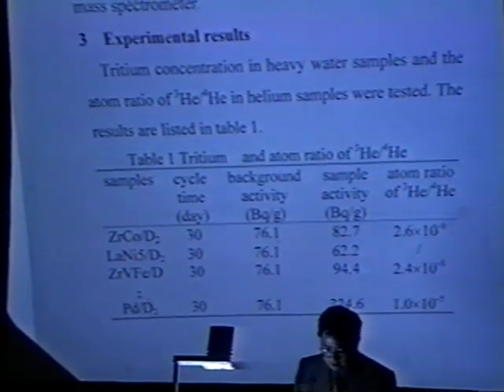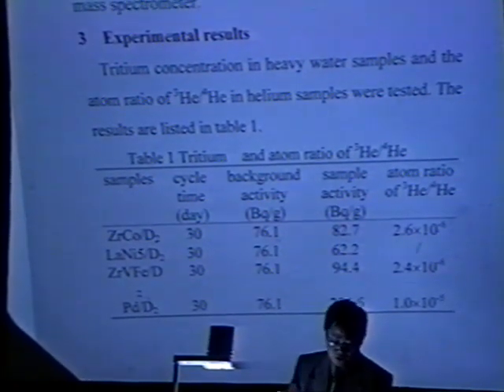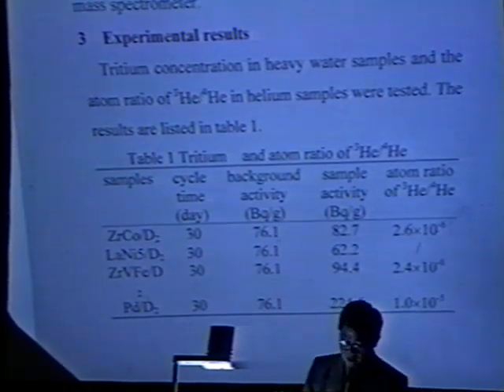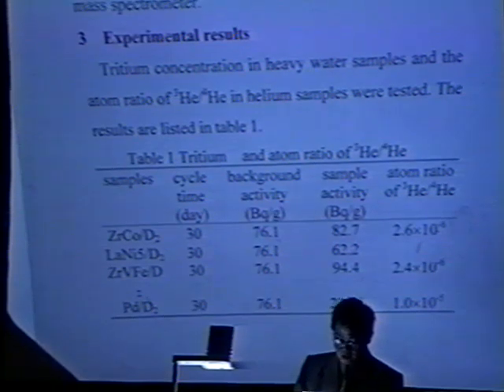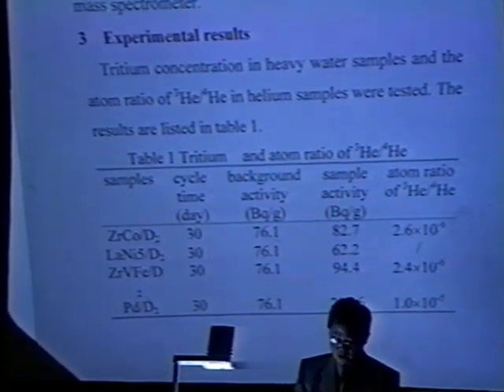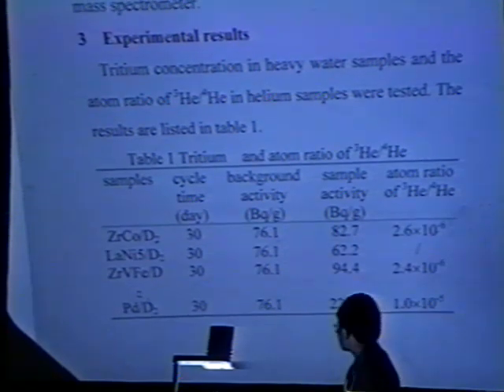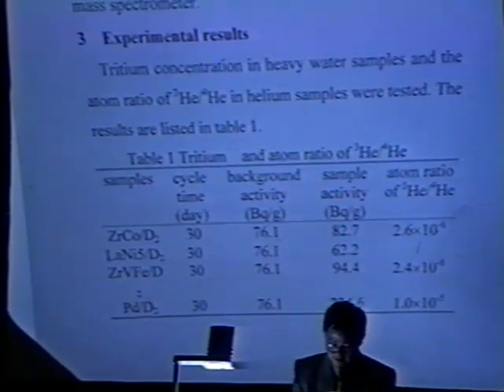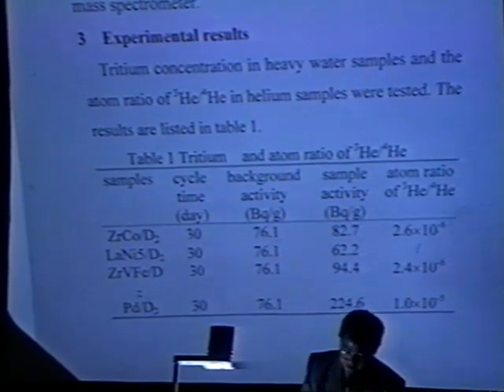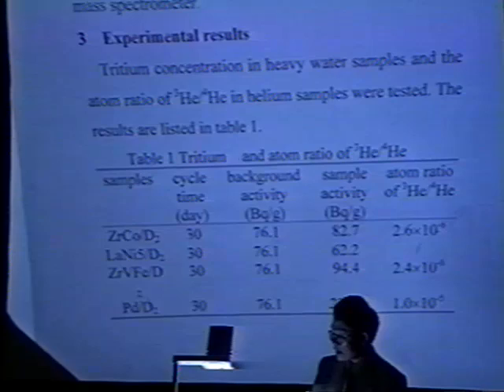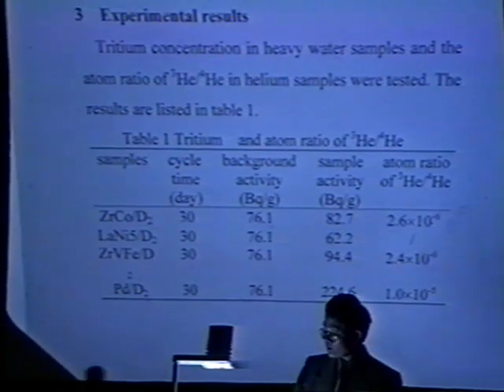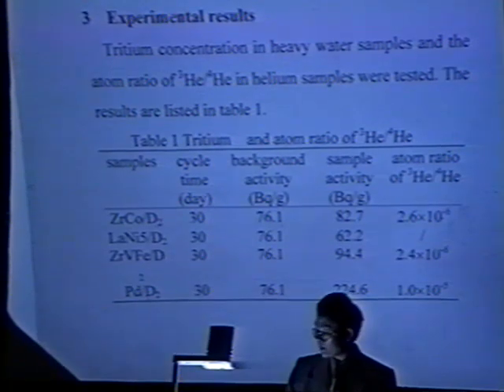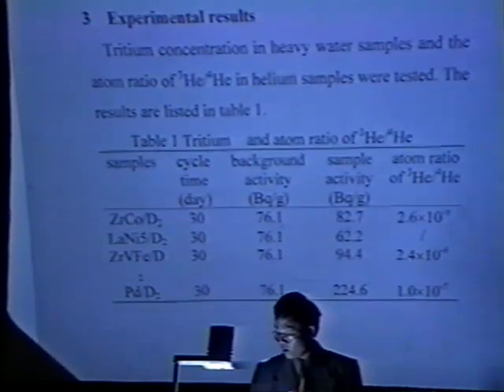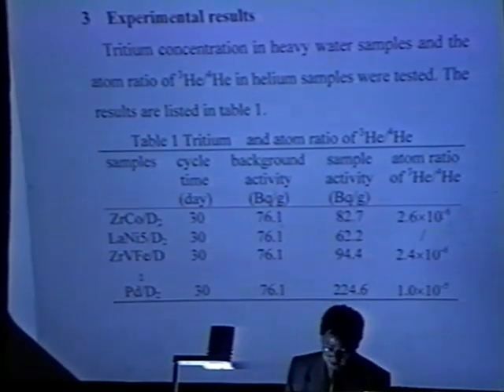So let's see the experiment results. Tritium concentration in the water samples was tested using LB+1 scintillation counters. The atom ratio of helium-3 over helium-4 in helium samples was also analyzed using an MM3000 mass spectrometer. The results are listed in Table 1 through Table 5. As shown in Table 1, only in the palladium deuterium system were both tritium concentration and the atom ratio of helium-3 over helium-4 greater than the background.